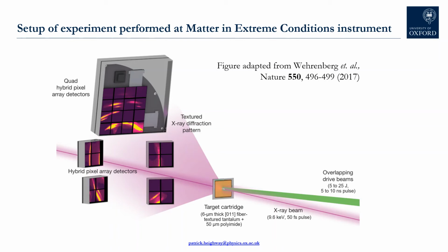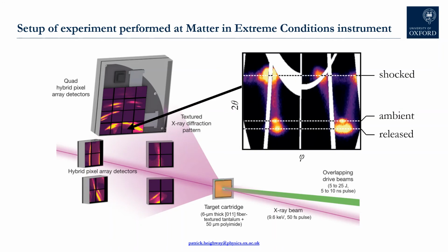The texture of the foils is such that each grain has its 011 direction closely aligned with the loading axis, and the foils are probed with the X-ray free electron laser as they are releasing, and the resultant diffraction patterns are then recorded on a set of Slac Cornell pixel array detectors. Now, the inset in the top right shows some archetypal diffraction data obtained during shock release.